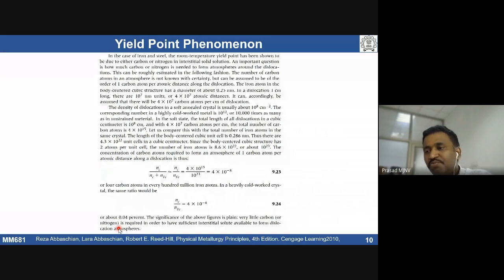Okay, so we need to have a small amount of carbon that can form a Cottrell atmosphere, that can lock the dislocations. To unlock the dislocations, we need a high stress. Once unlocked, it requires low stress for the propagation, for the plastic deformation to take place. So this is a concept given by Cottrell and Bilby.